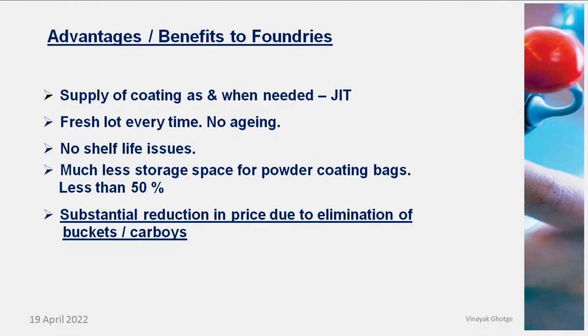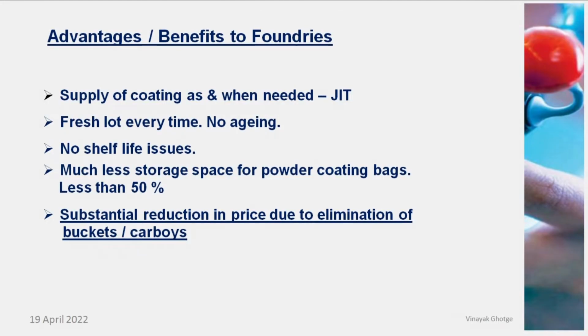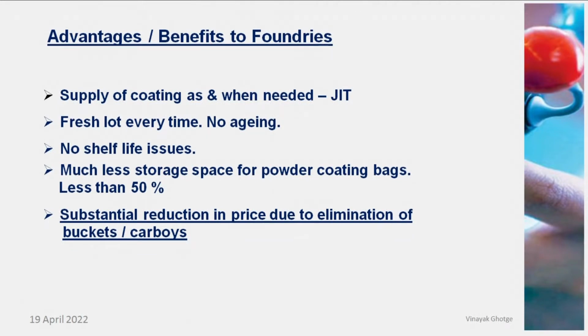What are the advantages of using powder coating versus ready for use or paste form? The supply of coating is just in time, a fresh lot every time, so there is no aging, no bacterial attack, no shelf life issues. And the most important from a storage point of view, less than 50% of the storage space is required, because these are all bags which can be stacked one over the other. The powdered product has a shelf life of 1 year, and unless it is tampered with or gets mixed with water, the product doesn't deteriorate. So there are absolutely no shelf life issues for the product.